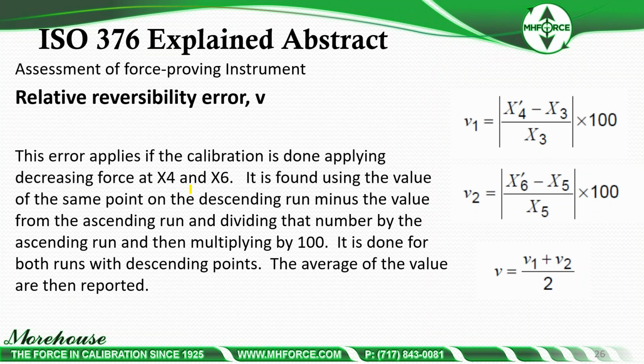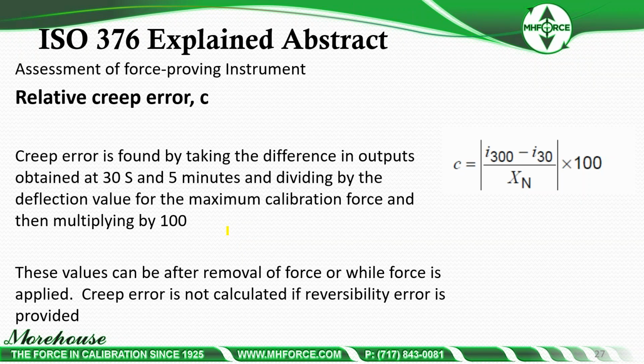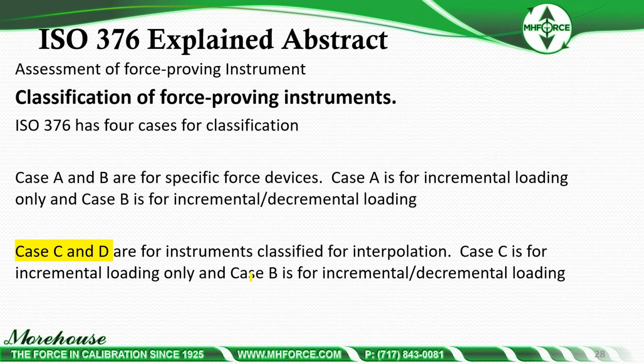This is, if you're doing this, it's only at x4 and x6. The descending measurements, and it's found by using these equations, and then you report the average value. There's creep error. Creep error is found by taking the difference in outputs obtained at 30 seconds and 5 minutes, taking those differences. And then you do all of that math, and then you can classify the force proving instrument.